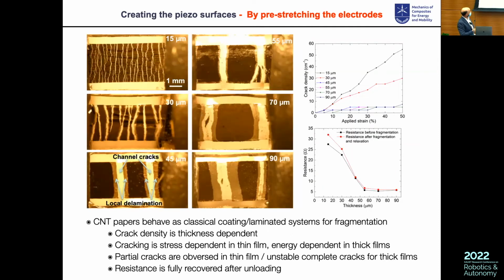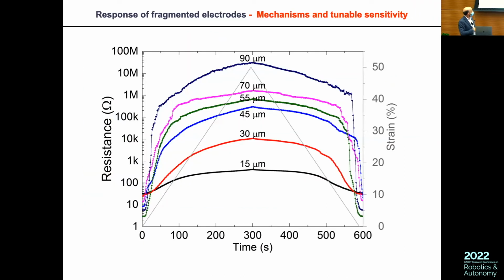And then what is very interesting to observe, you can do it with different thicknesses. I will not go into detail on this today, but depending on the thickness, you observe all the classical mechanics of thin films. That means if you work with very thin films, you get cracks that are not percolated. If you go to thick films, you get well-percolated cracks with low density. Everything is very compatible with the classical mechanics of thin films.